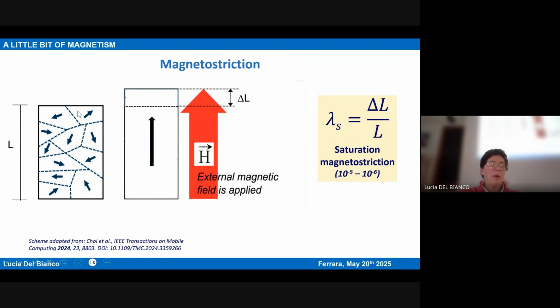If you start from a ferromagnet subdivided into domains, so it's not magnetized actually. If you apply an external magnetic field that magnetizes the material, you also observe a change in length of your sample in the direction of the applied field. So if your length increases, you have a positive magnetostriction, otherwise you have a negative magnetostriction. And at saturation, the magnetostriction is a mechanical strain, which is given by this ratio, delta L divided by the length of your sample. So this strain is a small effect. But it has very, very important consequences.